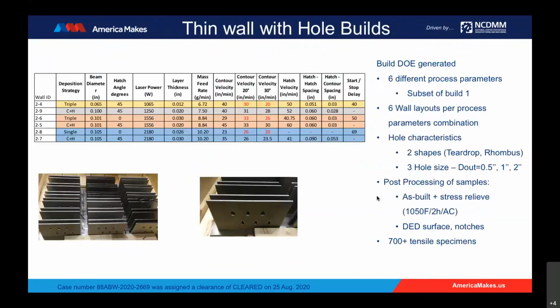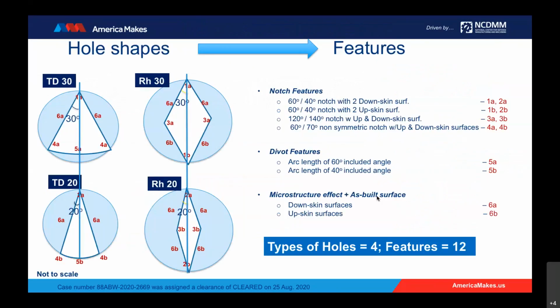Next slide, please. So to go over the matrix for the thin wall with holes, we've had 6 different process parameter sets. Some of them were subsets from the thin wall build process conditions, and a few of them were IDACE predictions forecasted to improve the process domain that was studied under this program. We had 6 different wall layouts per process parameter, where we changed the hole shape between a rhombus and a teardrop and the overall geometry of the hole feature. From this setup, we ended up with about 700 plus tensile specimen measurements, which we've used for creating BHM models and framework.